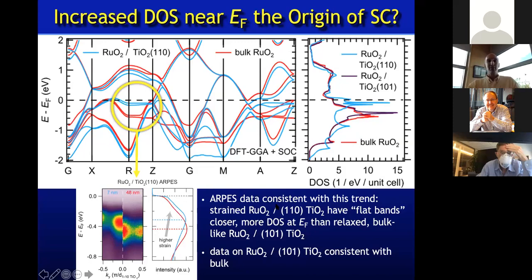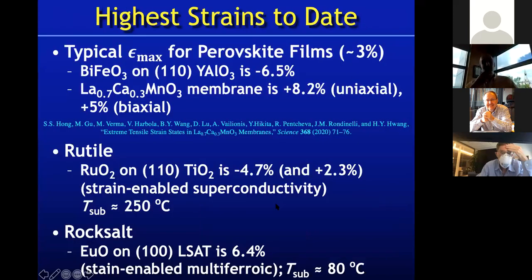Okay. Now I thought I'd also show another non-perovskite system with a crazy value of strain. Okay, a rock salt, and here the strains that we're trying to impose on europium oxide by growing it on LSAT are over 6% biaxial compression, and you must think, this guy is totally off his rocker. But let me point out that my postdoc has gone to incredibly low growth temperature. This is again an advantage of getting away from the perovskites. Rock salts can be grown at very low temperatures.